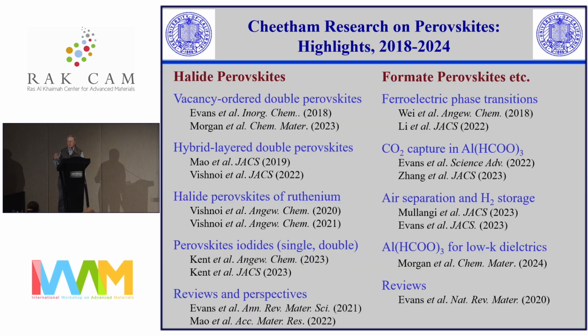But what we've been doing in the last 5 years or so has been to continue work on the halide perovskites, focusing on things like double perovskites. Pratap Vishnoi mentioned some of the work that he did when he was in Santa Barbara on ruthenium. Highlights just recently, we've trebled the number of known single perovskite iodides, hybrid iodides. So we've made things like methylammonium rare earth iodides and methylammonium strontium iodide and so on. So this family is actually bigger than people had thought. I was absolutely amazed that nobody had tried to do this, or if they did try to do it, they didn't succeed. But we've made this and just published it in JACS just at Christmas time.